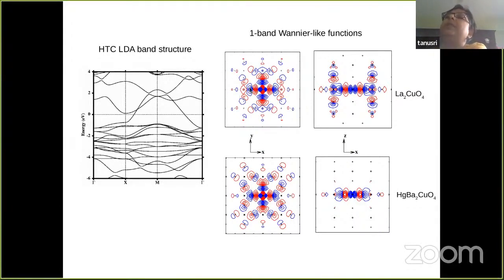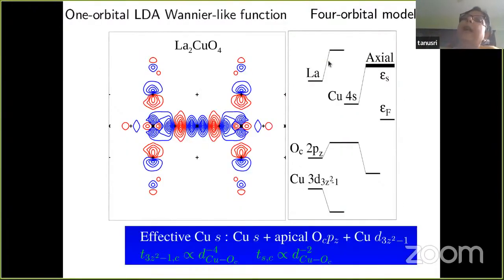For the lanthanum compound, it is much more localized in plane, while for the mercury compound, it's much more delocalized in plane. On the other hand, for the lanthanum compound there is quite an appreciable out-of-plane extent, but for the mercury compound it is completely confined to the plane. So already this wave function shows quite a big distinction between the lanthanum and the mercury compound. And from the out-of-plane composition of this wave function, you can conclude something about the out-of-plane extension of this effective wave function that basically describes the single band crossing the Fermi level.